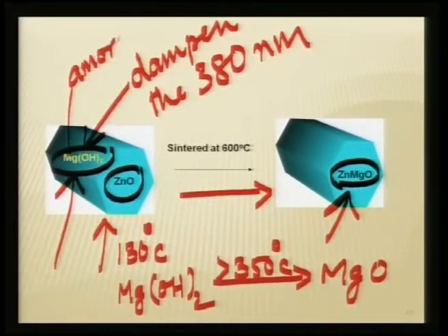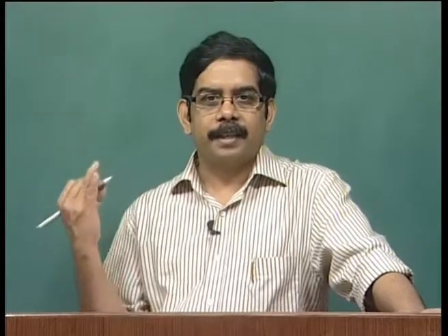So it is very deceptive. Why does magnesium hydroxide not show in X-ray? Because this is an amorphous phase. So in X-ray you would see a clear zinc oxide pattern coming out, whereas magnesium still remains as a hydroxide and has not really got substituted.